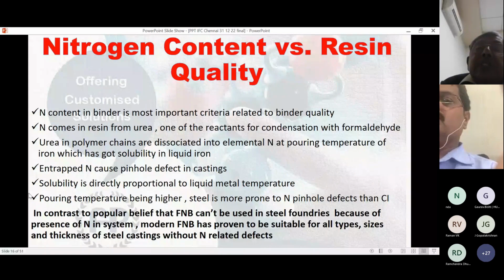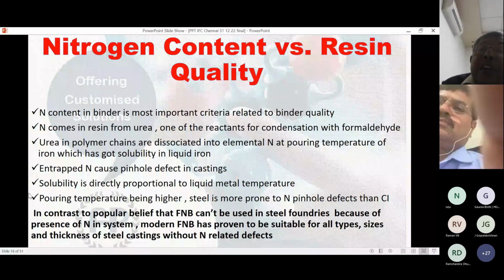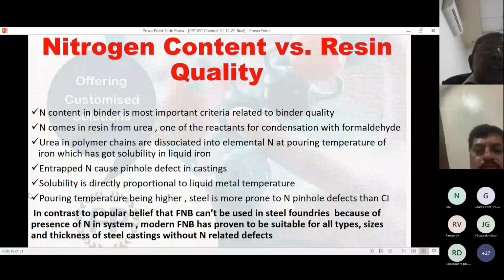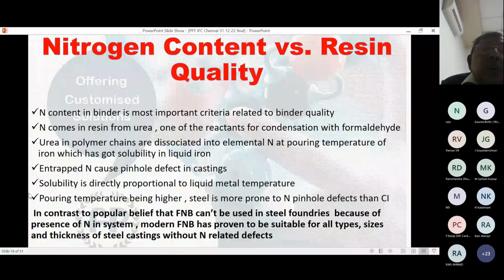Nitrogen content versus resin quality. Nitrogen content in binder is the most important criterion related to binder quality. The higher the nitrogen, the lower is the quality. Nitrogen comes in resin from urea, one of the reactants as you have already discussed. Urea in polymer chains is dissociated into elemental nitrogen at pouring temperature of iron, which has got solubility in liquid iron. Entrapped nitrogen causes pinhole defect in castings. Solubility is directly proportional to liquid metal temperature. Pouring temperature being higher, logically, steel is more prone to nitrogen pinhole defects than cast iron.